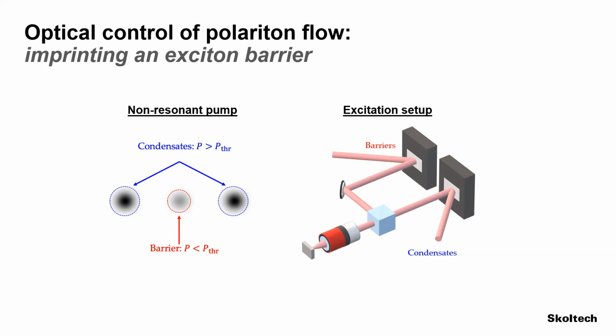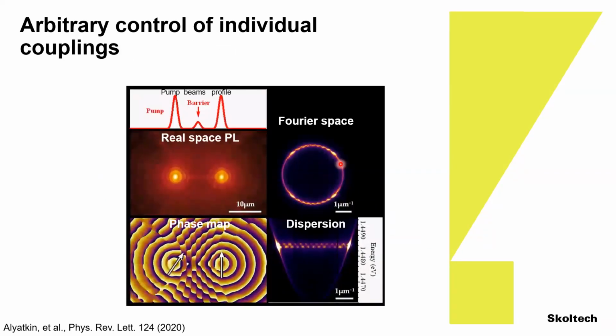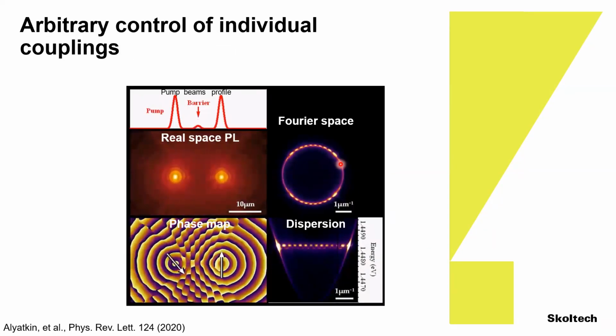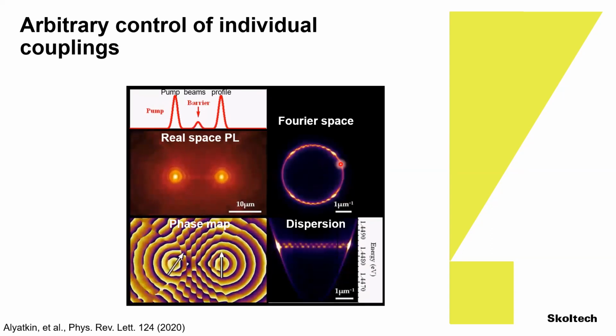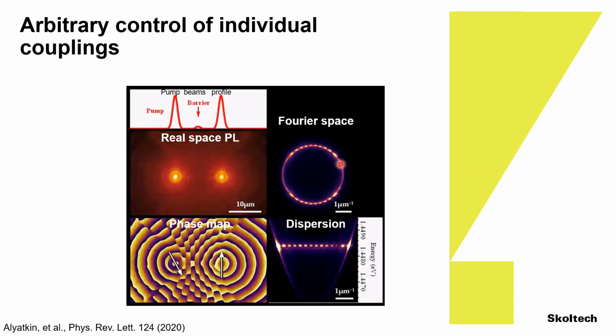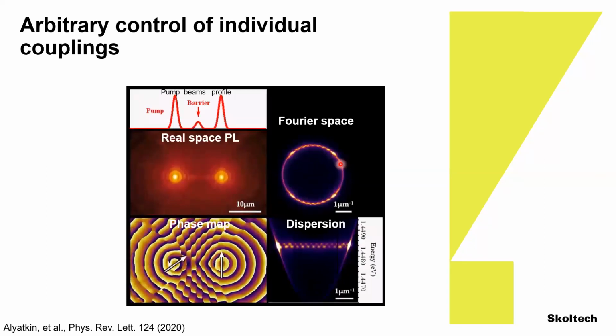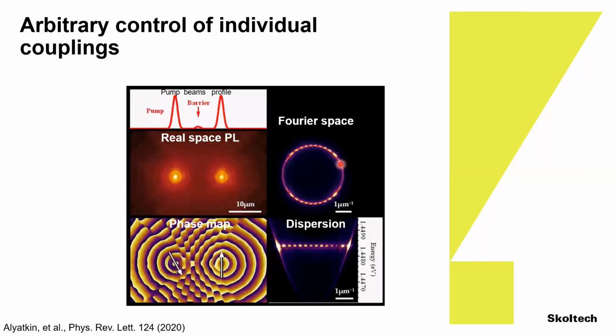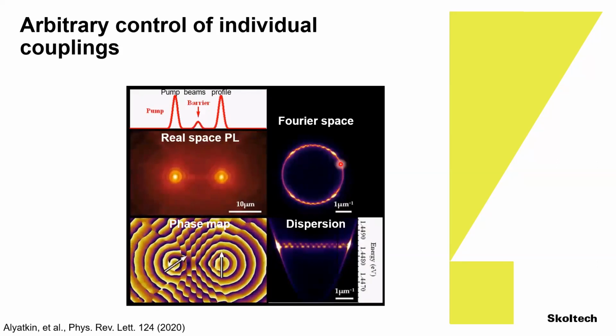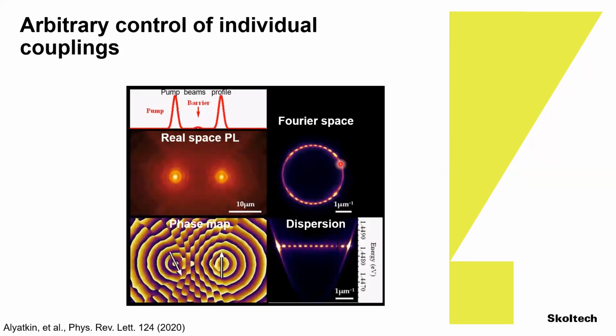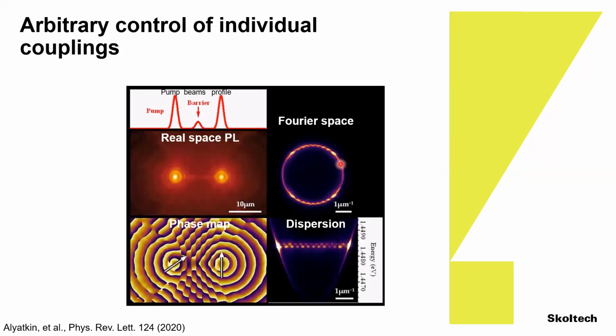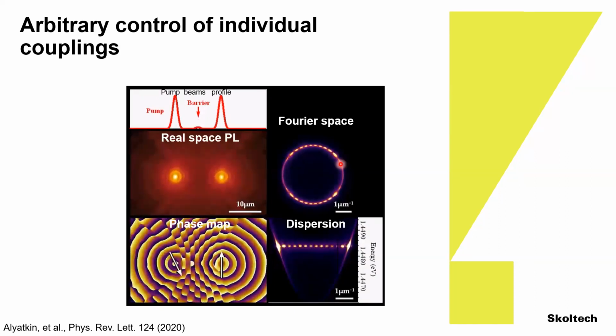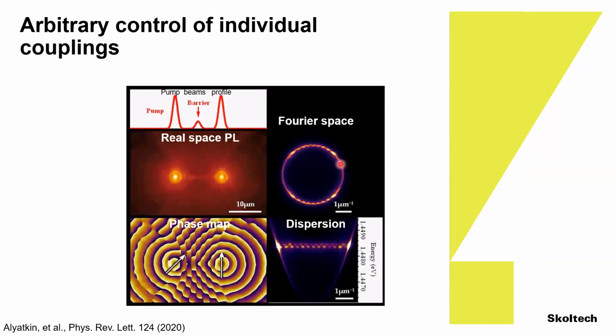And when I look now at the pumping profile, the sub-threshold exciton reservoir acts as a barrier. These are the two condensates in real space, and in reciprocal space a ring, with fringes because they are coupled. And when I do homodyne interferometry and I measure the relative phase, by scaling the height of the barrier, I can control the coupling of the two condensates from being in phase or out of phase in a continuous way. So this potential barrier impedes the flow between the condensates so that it allows me to control the Jij.